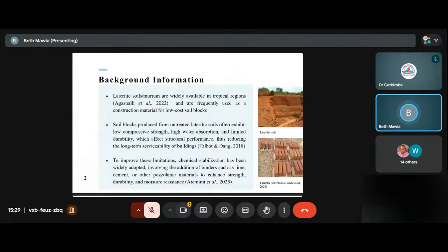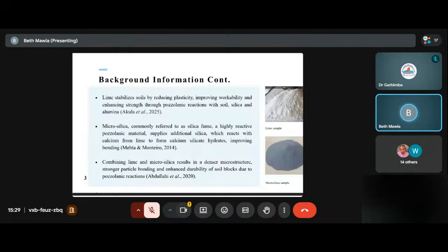Background information: lateritic soils are widely used for low-cost construction blocks in tropical areas because they are readily available and cheap, but they often have problems like low compressive strength, high water absorption, limited durability, and this may limit their construction application. Therefore, chemical stabilization has been adopted to counteract this, and lime is one such additive. It improves soils through pozzolanic reactions. Microsilica, which supplies high silica fume, is also used to supply additional silica, and when it reacts with lime, it forms the cementitious calcium silicate hydrate, through pozzolanic reactions.